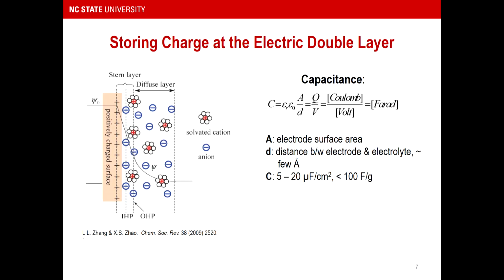So what happens at the electrochemical interface is we're storing charge at the electric double layer. And the reason the capacitances of these devices can be so much larger than a dielectric capacitor is that now the separation distance between our positive and negative charges are essentially what is formed at that electrochemical interface. So each electrode interface is a separate capacitor. And that distance between the positive and negative charges is just a few angstroms. And that's the critical thing that electrochemical interfaces afford.